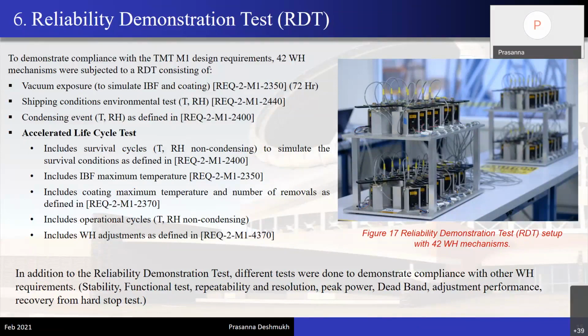So hence we did this RDT testing by using 42 warping harness mechanisms. Now why 42? I'll explain in the next slide. But we prepared such 42 test setups and installed them in an environmental chamber. Of course, before going to the environmental chamber, we did component level vacuum exposure testing in a vacuum chamber, followed by these environmental testings.